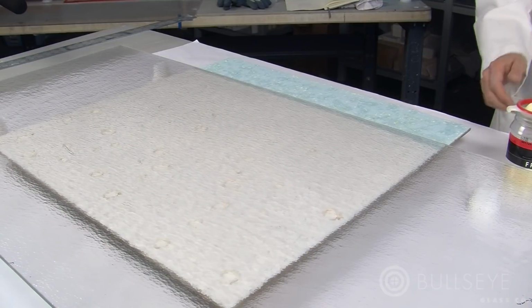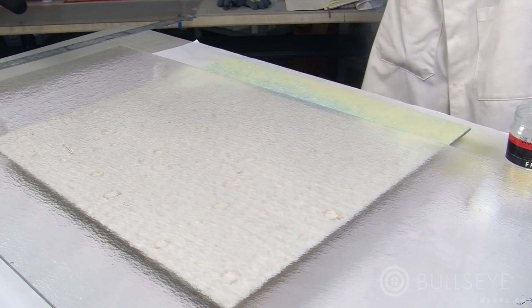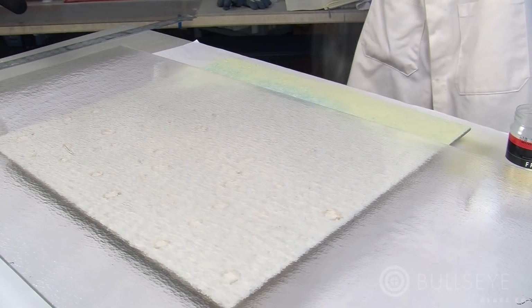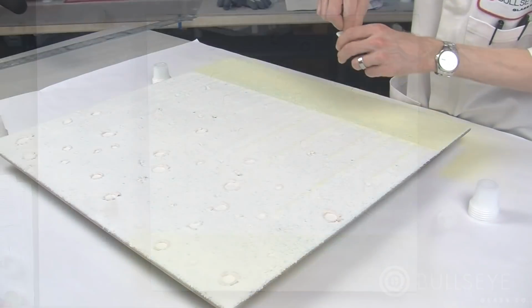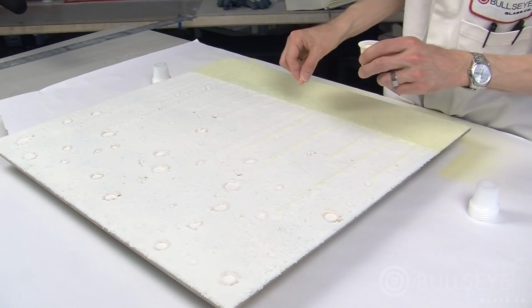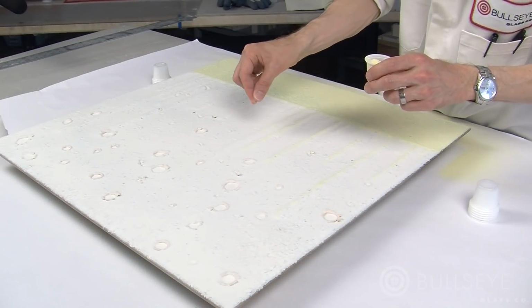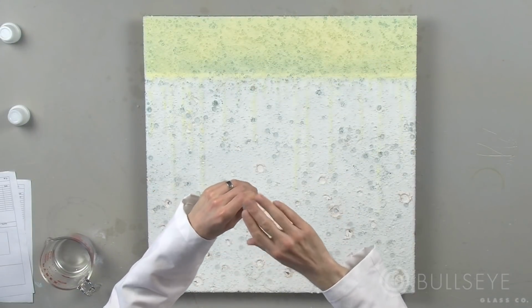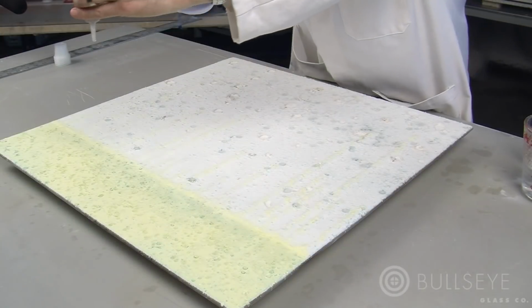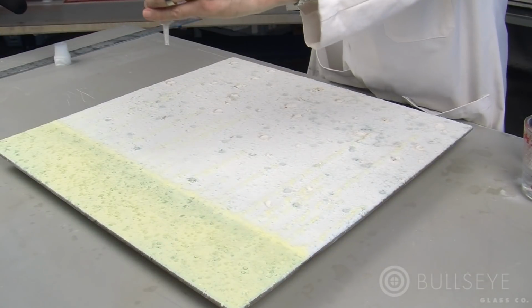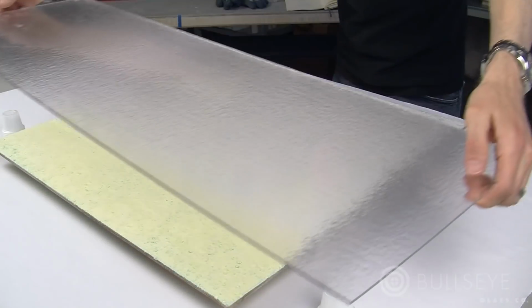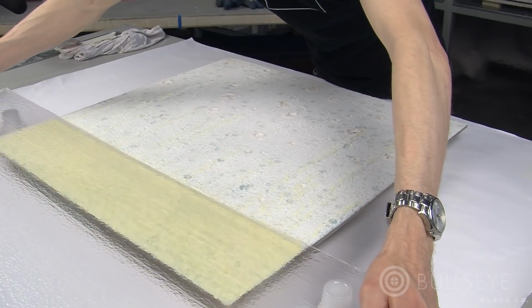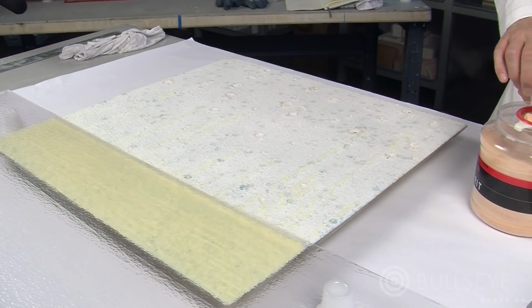And I put 2 more cups of 1125 orange powder in that upper area, and reclaim my overspill. And then I put about a half a cup just by pinching it between my fingers along those drip lines. Then I go over the whole thing again with water and a syringe to create more impacts and craters. So I'm getting a really heavily distressed and pitted looking surface by doing all of this.